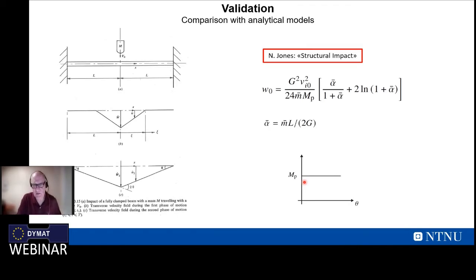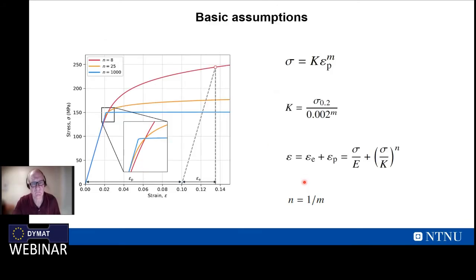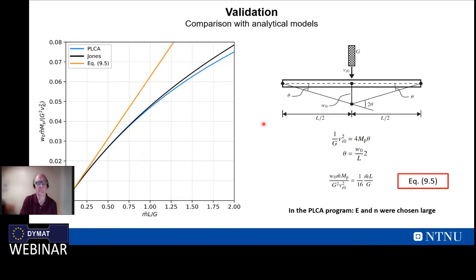Now we have compared this solution with this mode approximation technique. When you are going to compare, he has a perfect plastic material. So here we need to put E equal very large, almost infinity, and then we need a large value of n. So we have an almost rigid, perfect plastic material in the spreadsheet. And here, this is the Norman Jones solution. This is the displacement, dimensionless, as a function of the mass ratio. The black curve is the exact solution by Jones, and the mode approximation technique gives you this. Yeah, so very good